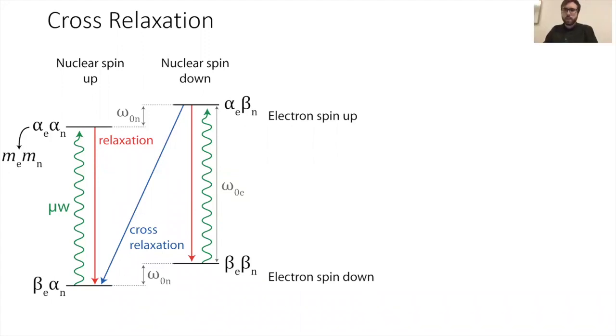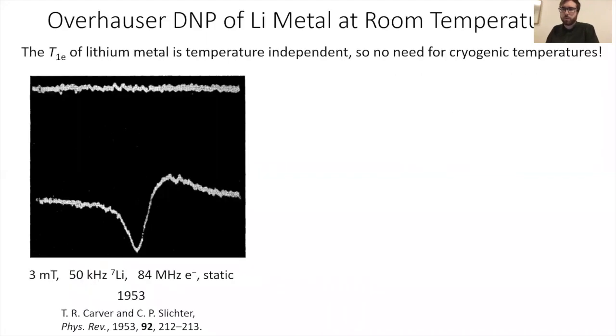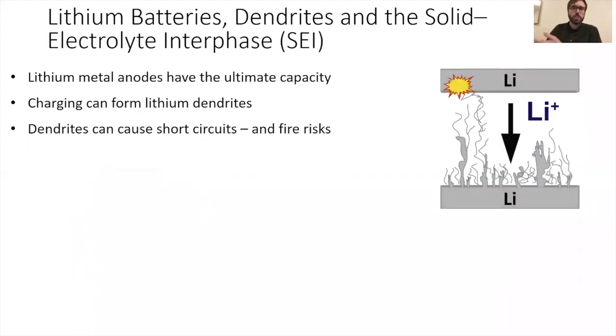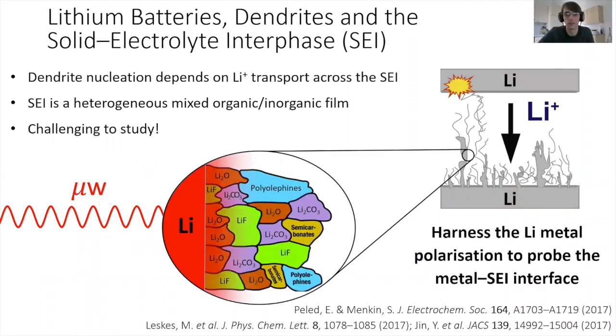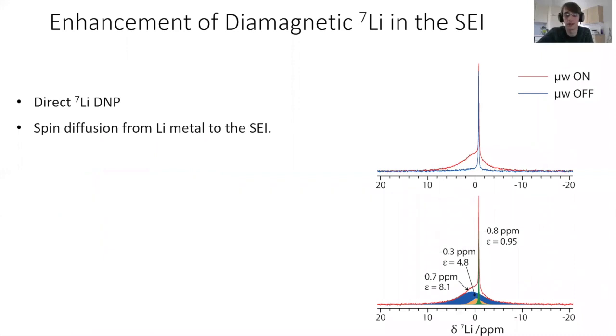All right, and Scott Carnahan has a question here: why does the lithium-7 spectra show hyperpolarization around 0 ppm and not shifted to plus 300 ppm? I know you need peak overlap to cause spin diffusion. How do you explain how the metal was able to polarize the diamagnetic phases? So this is maybe still an open question. There are two possible ways that you can imagine hyperpolarizing a diamagnetic lithium. One is you hyperpolarize the lithium in the lithium metal, so the lithium-7 in the lithium metal, and then you get spin diffusion.